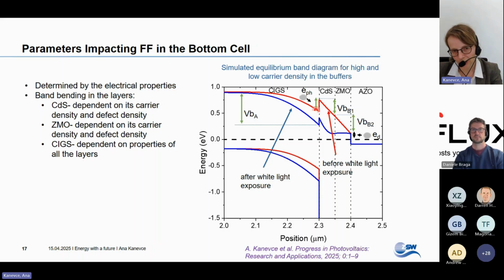If you look at, so now the red band diagram, the Fermi level here is in the middle of the bandgap. And this makes it beautiful for non-radiative recombination at the interface. If the buffer layers are highly doped, the conduction band is close to the Fermi level, and then we have many electrons here, but not many holes, and the device is more tolerant to recombination at the interface. Now, what can we do to increase the doping in the layers? And which one is more important? Is it cadmium sulfide? Is it zinc magnesium oxide? Which one can we concentrate on?